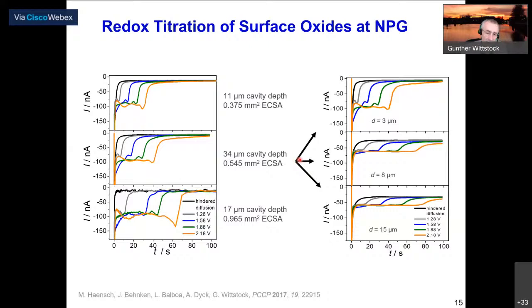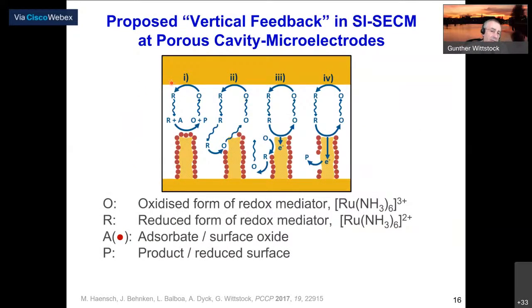to highlight why this is so surprising, we took this electrode, and now we varied the distance between the interrogator electrode and the cavity electrode. So we varied the outer distance. And then you see even a slight change of that distance makes the current go down, but also makes the slope at the end of the titration more drawn out the further away the interrogator electrode is, because that disperses the times for the mediator to reach the sample and titrate. So why is that? Our explanation is, if we start the titration, we titrate the outer surface, and then afterwards we can go on with two mechanisms.